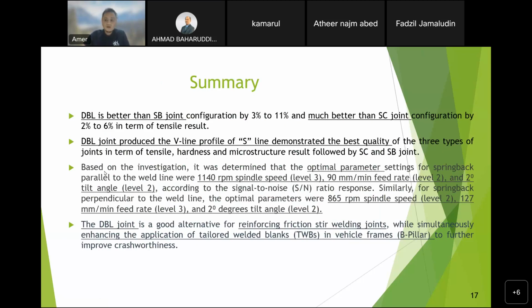Based on the investigations, it was determined that the optimal parameter setting for springback parallel to the weld lines was 1140 RPM spindle speed, 90 mm per minute feed rate, and 2-degree tilt angle. For springback perpendicular to the weld lines, the optimal parameters were 865 RPM spindle speed, 127 mm per minute feed rate, and 2-degree tilt angle, level 2.